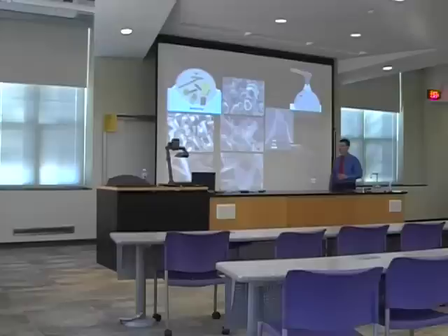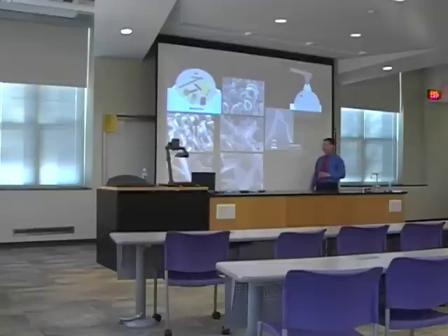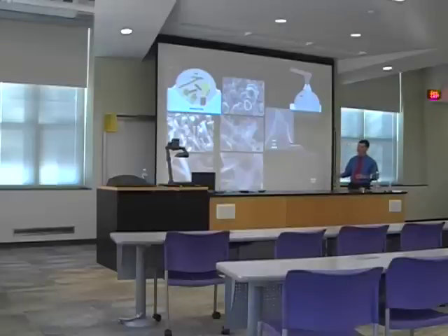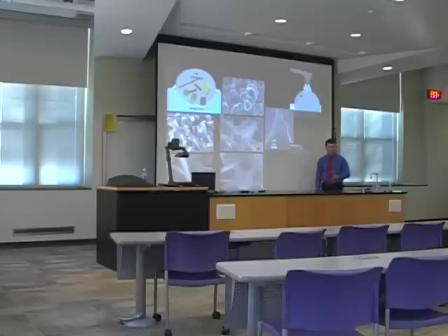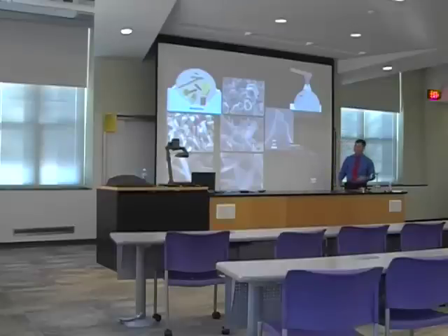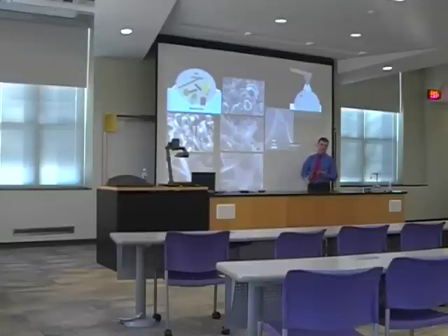So let's start with metal gallium alloys. The origin of this experiment is really interesting, because of how we originally obtained all these nanostructures. One of our undergraduate students was making experiments on propagation of liquid gallium on different metallic foils, just basically measuring the speed of propagation to find the diffusion coefficient. After he coated the metallic foils with gallium, we etched them with hydrochloric acid and decided to take a look at what happened with the surface.